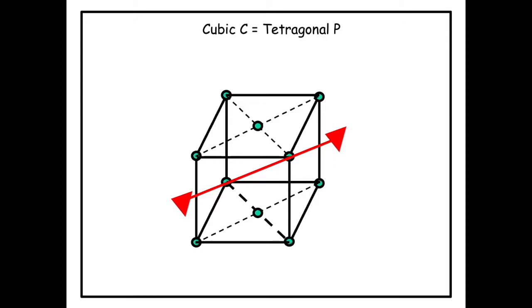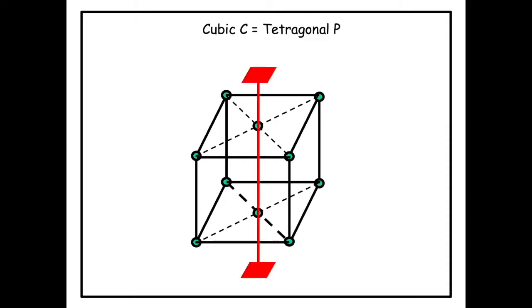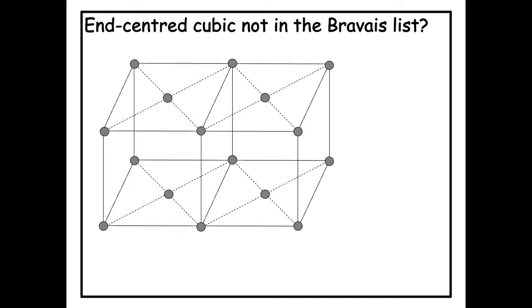The three-fold axis cannot exist with the centering of top and bottom faces, because this axis permutes the top face with the front face and the front face with the right face. But now the top face and front face are not identical — one has a centering lattice point, the other does not. So this axis is no longer a three-fold axis and disappears. However, the lattice does retain one 4-fold axis — and this is the only 4-fold axis. So this lattice has one 4-fold axis, making its crystal system tetragonal.